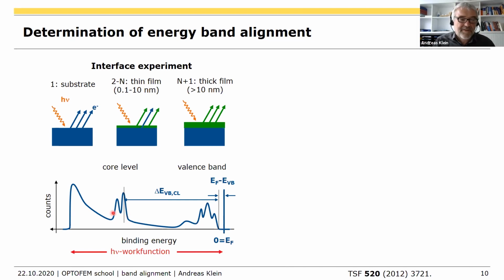So this is a materials constant, the distance between the core level and the valence band maximum. And what we're now doing, and that's a good thing, because when you deposit a material on top, your valence band emissions will change, because here you will have a superposition between the valence band states of the substrate and the valence band of your deposited film. This is not the case for the core level, because the core level of your film is usually different because it contains different chemical elements. So these core levels are very specific to the elements.